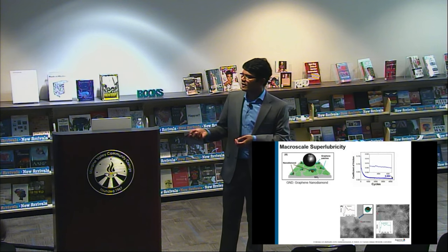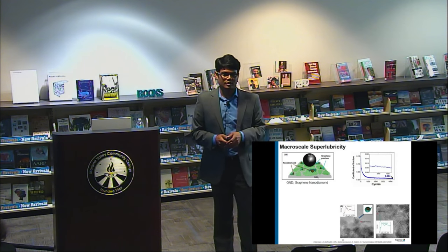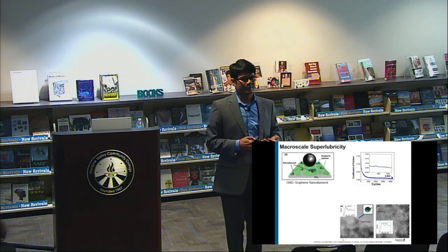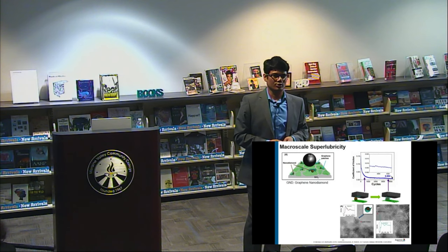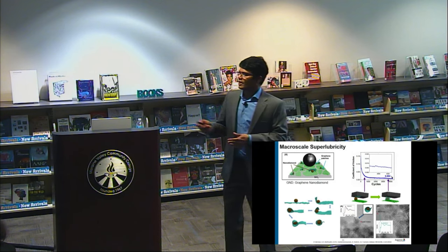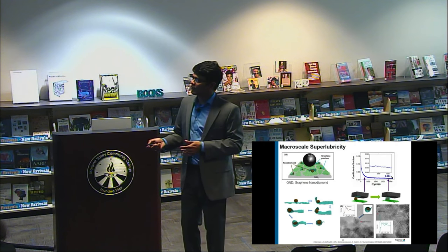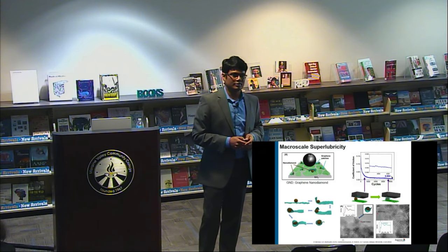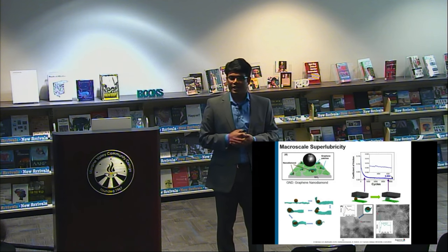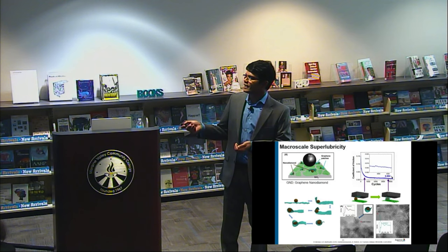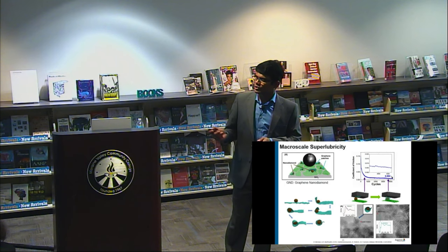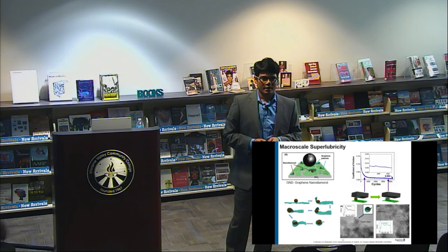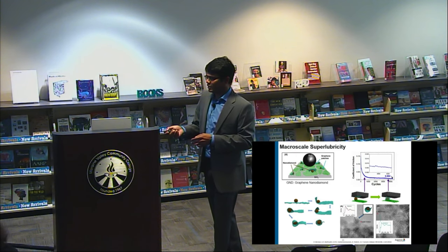It shows us what has happened, how the material was transformed, whether there is any chemical activity or physical activity. We also collaborate with the theory and modeling group to show that it is theoretically possible. It turns out that these nanodiamonds are wrapped by graphene into scrolls, and that provides very low friction at the end of the test. It is done at macro scale loads and speeds. This was a big breakthrough that came through Argonne CNM in 2015.